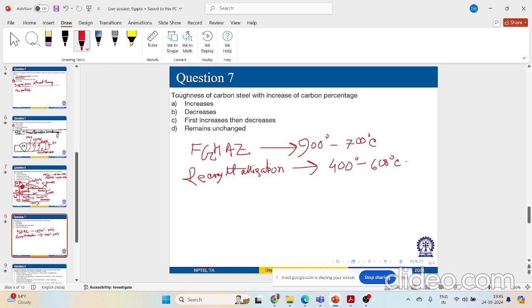Right? Now, if you are thinking with respect to retention period or soaking time, the high temperature retention period during welding in the heat affected zone is very short to develop a homogeneous solid solution of austenite, right? Through complete dissolution and phase transformation, especially in alloy steel having some stable phase compounds. So what will happen? A very inhomogeneous solid solution of austenite will form, along with other stable phases that will form in the heat affected zone. That will affect my transformation behavior of austenite. Correct? So yeah.